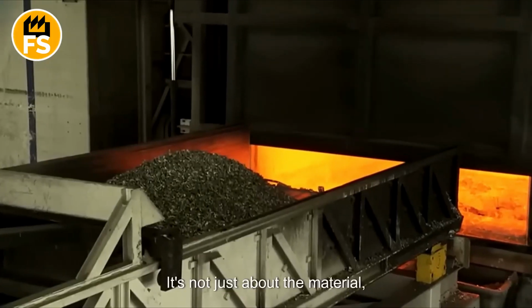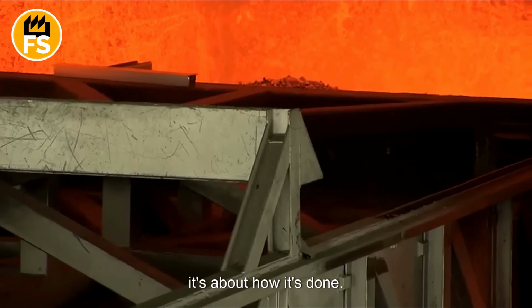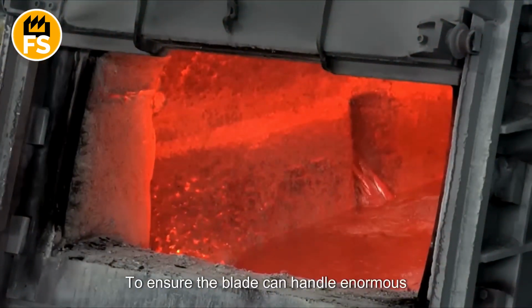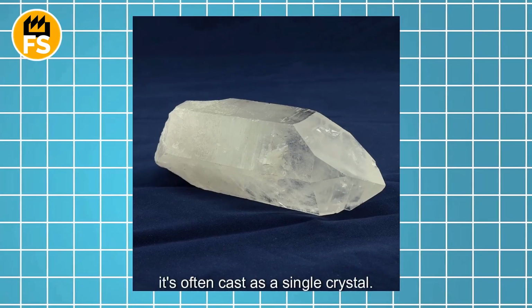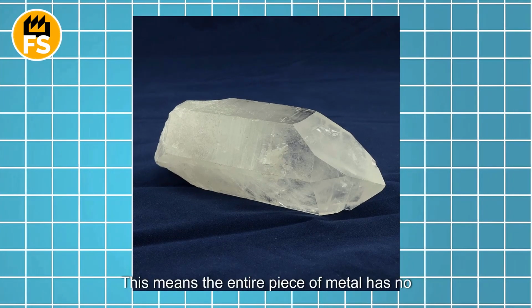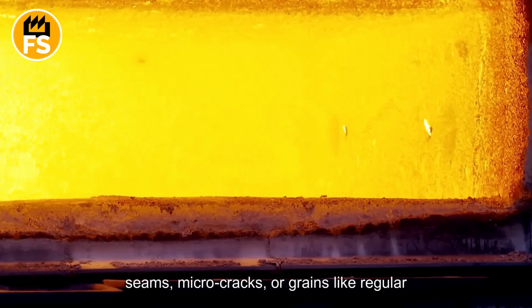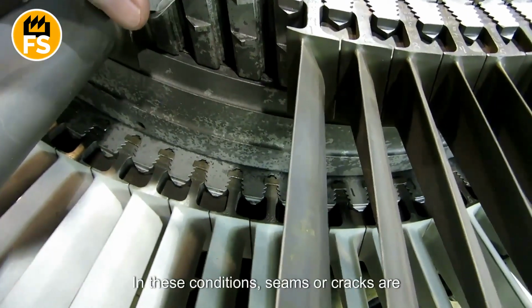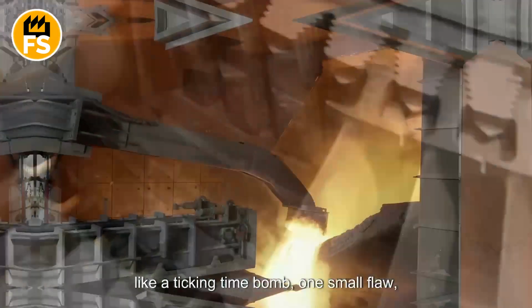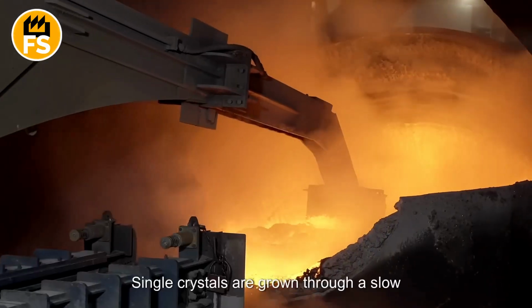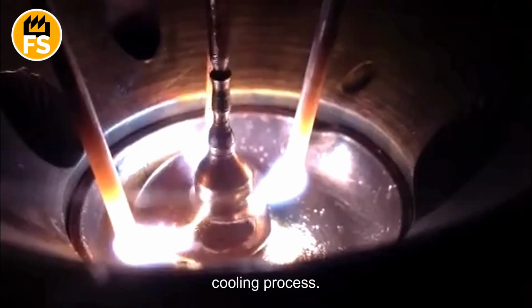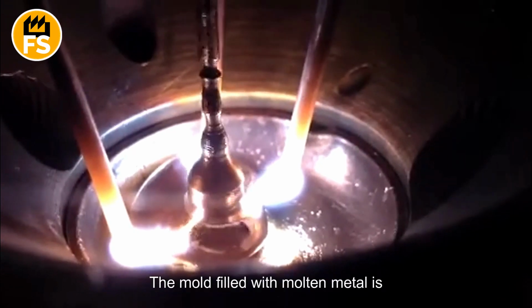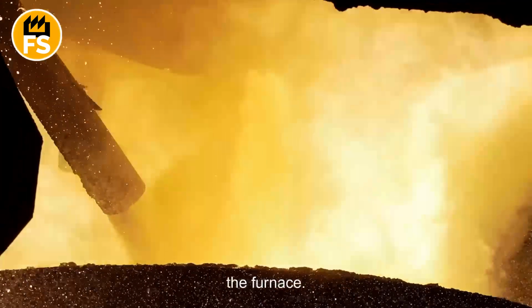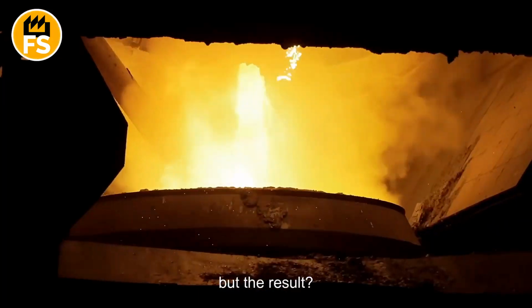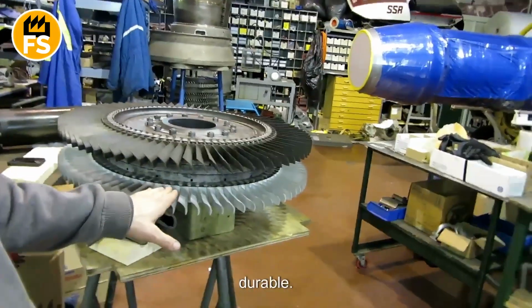But here's the catch. It's not just about the material, it's about how it's done. To ensure the blade can handle enormous temperatures and stresses, it's often cast as a single crystal. This means the entire piece of metal has no seams, micro cracks, or grains like regular metals do. Why is this important? In these conditions, seams or cracks are like a ticking time bomb. One small flaw, and the blade fails. Single crystals are grown through a slow cooling process. The mold filled with molten metal is gradually lowered into the cooling zone of the furnace. This process can take days, but the result? A blade that's incredibly strong and durable.